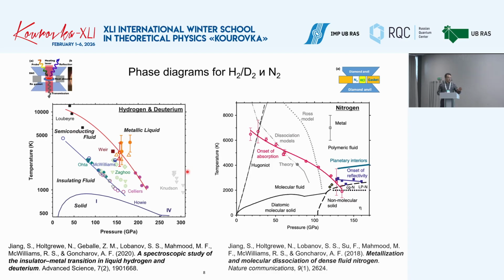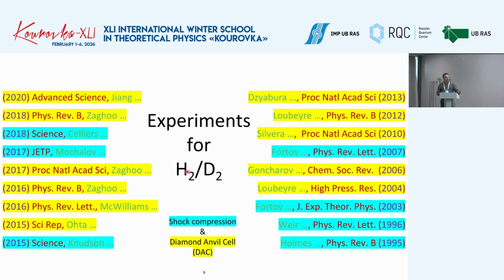So these are the phase diagrams for hydrogen and for nitrogen from the papers of the same group of Alexander Goncharov and co-authors. You see that for hydrogen, the number of points is larger, for nitrogen a bit smaller, but there are many similarities in these phase diagrams. If we look at the hydrogen case, the number of experiments is large, and in addition to diamond anvil cells, people used shock compression to study this phase diagram. And you see high rating papers.